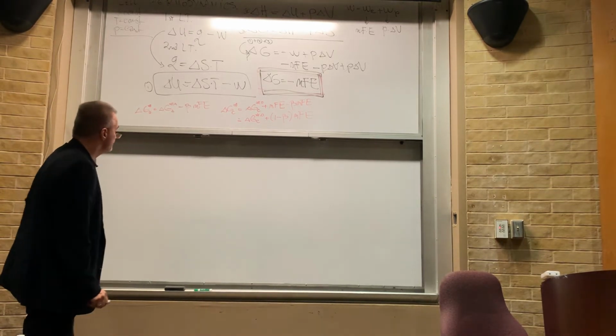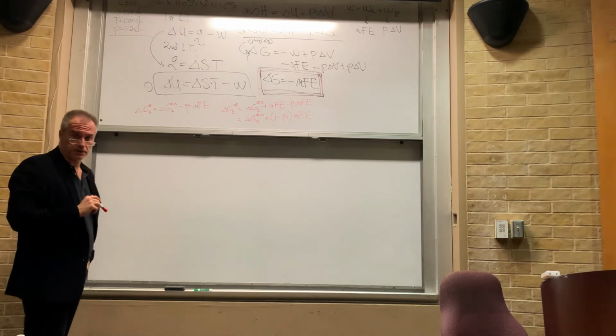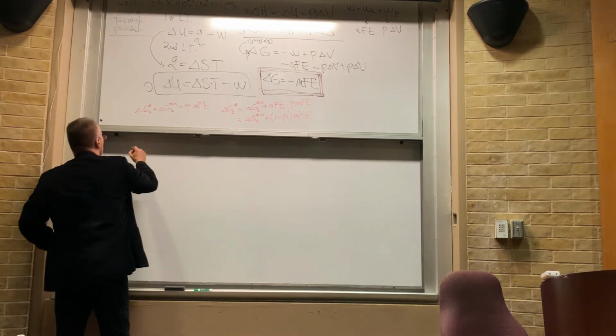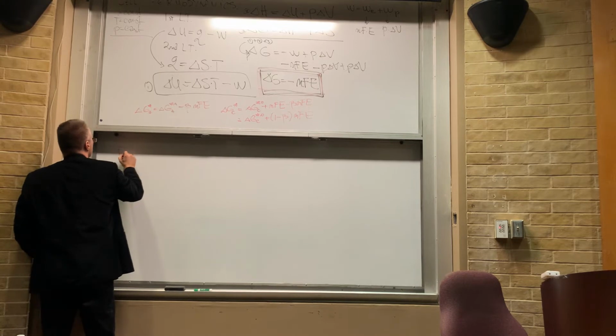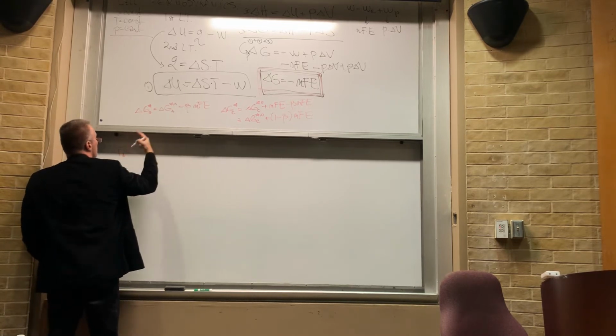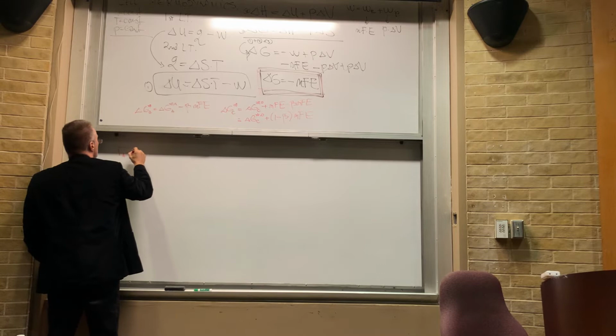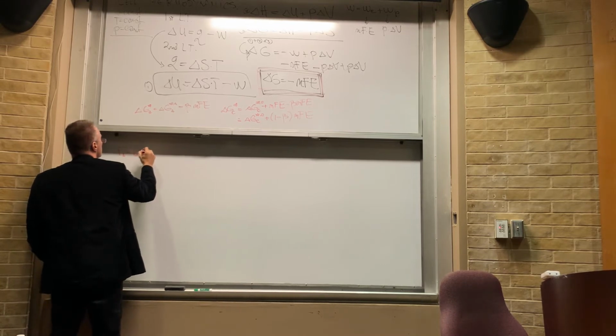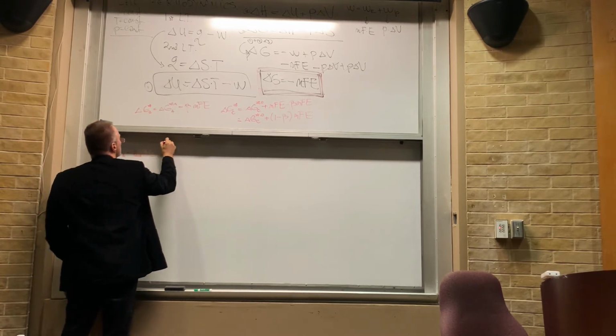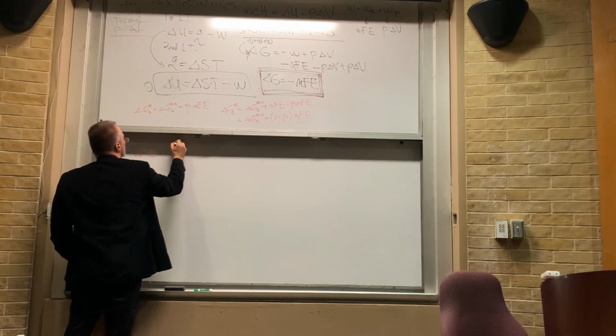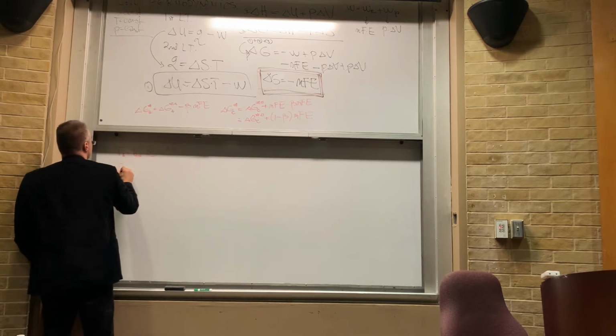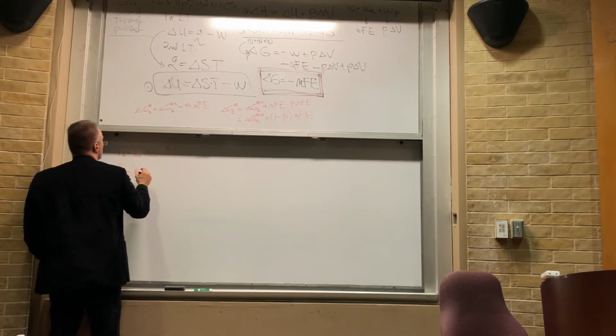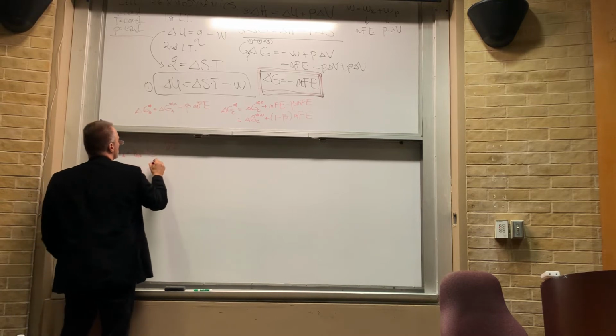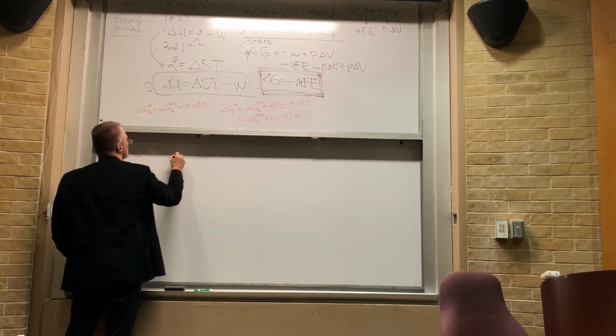Going back to the rate equations, as I said, the anodic rate is equal to K anodic, which we said is K naught anodic, e to the minus delta G hash anodic over RT, and the rate of the cathodic reaction is K naught C e to the minus delta G hash C over RT.